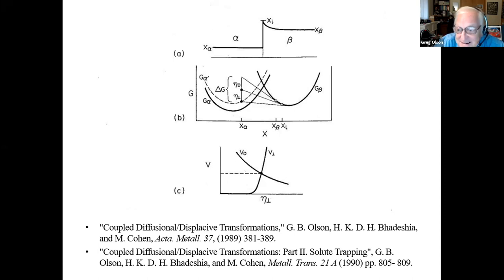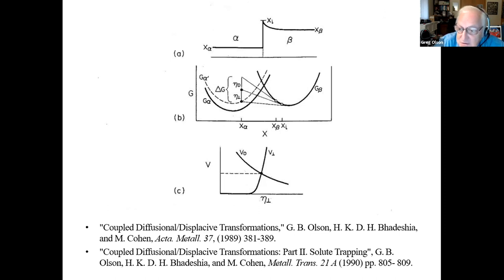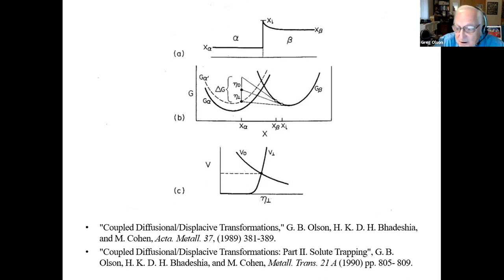I came to understand that in later years Jack Christian seemed to talk Harry out of this approach, but we stuck with it at Questek and coded it up. We made very good use of this framework as an extension of our martensite framework to control the hardenability in our designs of martensitic steels. Notably, we also had a commercial contract where a client used the output of our simulations to calibrate descriptive JMAK models in commercial heat treating software — an early example of generating data from fundamental simulation as an alternative to experimental dilatometry.